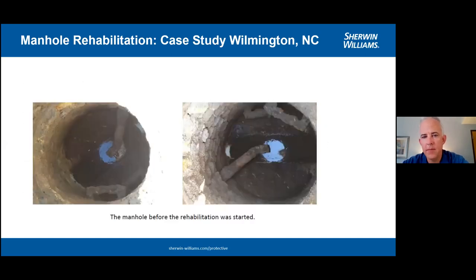And here's the befores. As you can see in the photos, there was about 2 to 3 inches of concrete gone in this structure. You can see all this carbonated concrete, which is basically just a paste or a powder that was still hung onto the wall. And you can also see where it's deteriorated all the way back behind that carbonated area as well. The photo on the left is not as good a representation because I took it on the shadow side first, but the photo on the right gives a real good representation of what kind of shape this structure was in before we started with it.